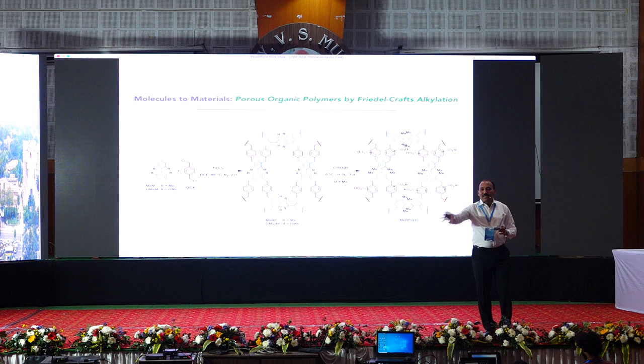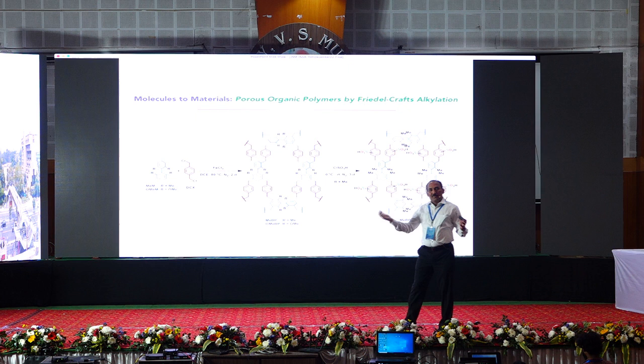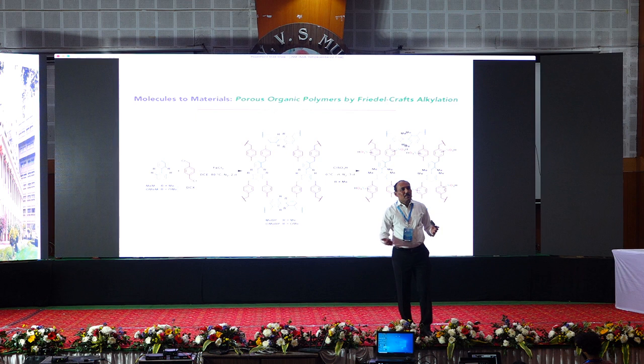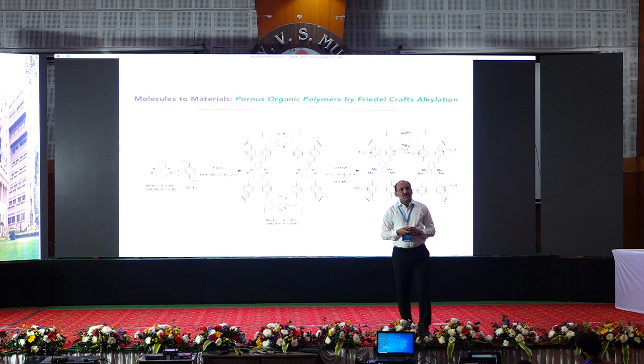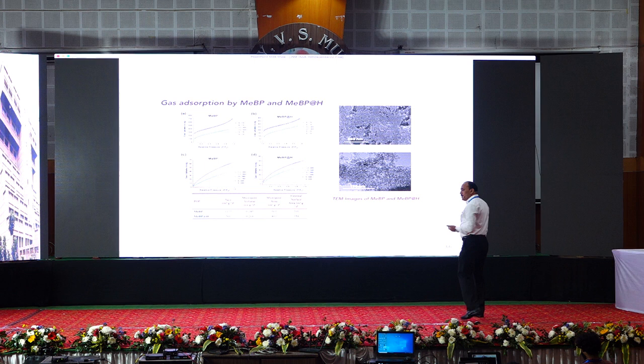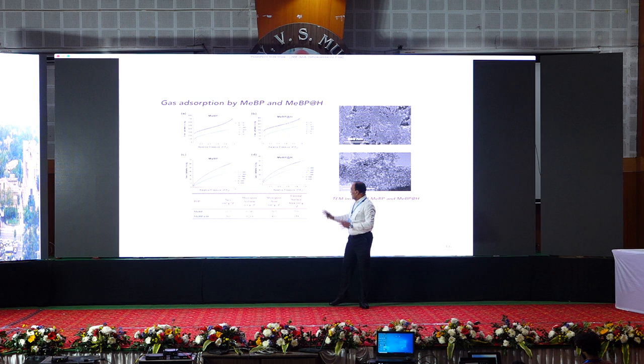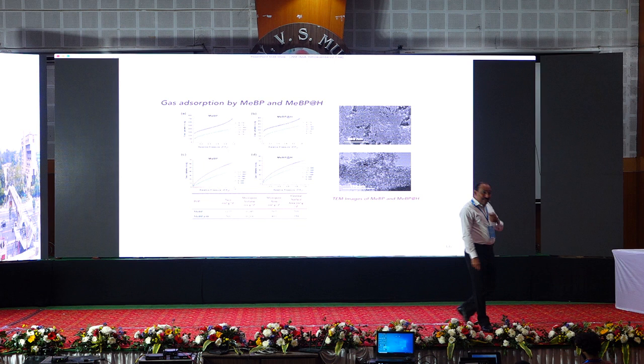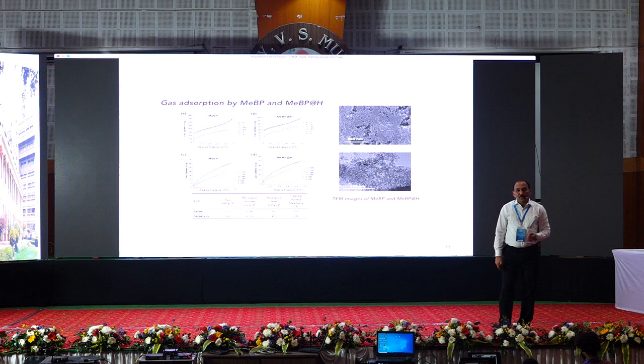Does it serve a purpose? Because of the pores inside, the reactants can go in and out. Material transport is easy, and the reactants can access these acid sites. The transformation should occur. How porous are they? Just to show you, these numbers are small in my polymer. It's only about 700 square meters per gram if you do the BET analysis. There are organic polymers known with 3,000 to 4,000 square meters per gram. You can engineer such a porosity.